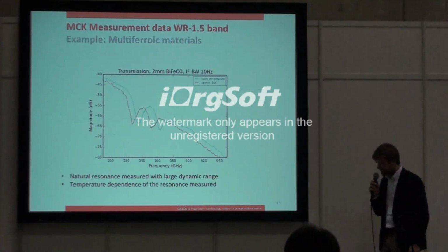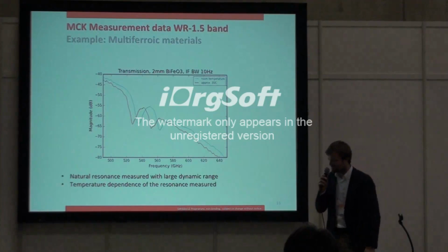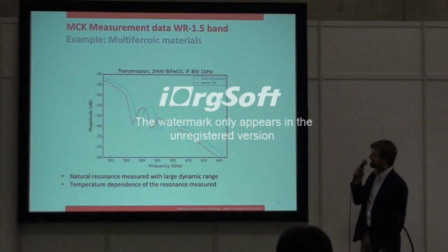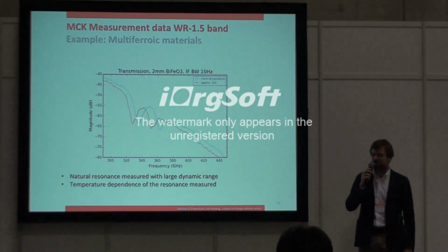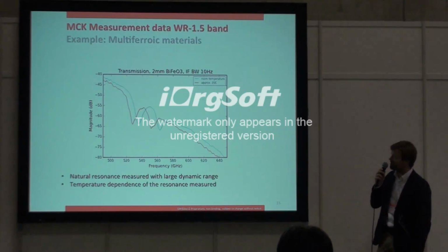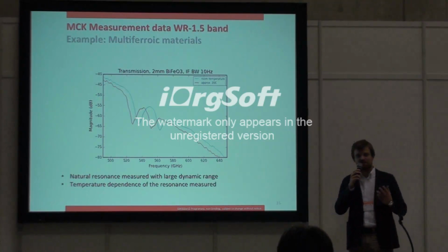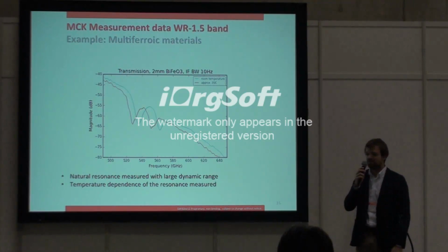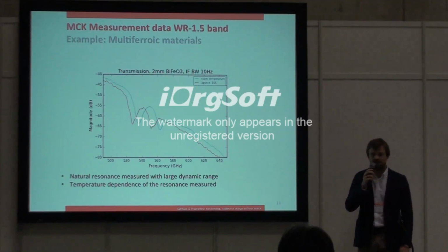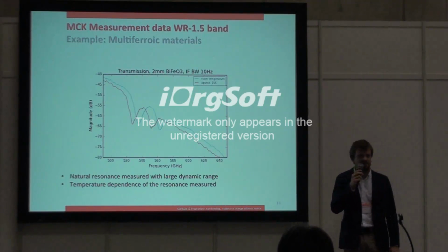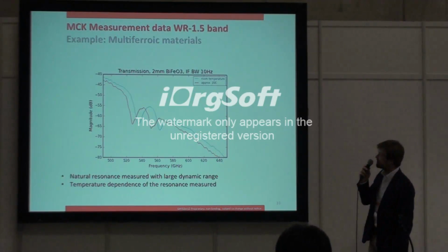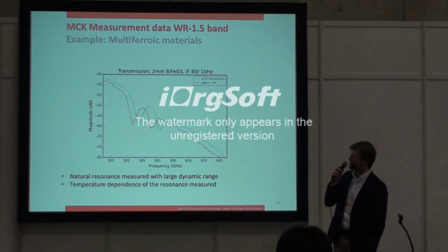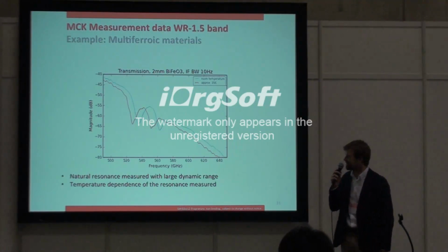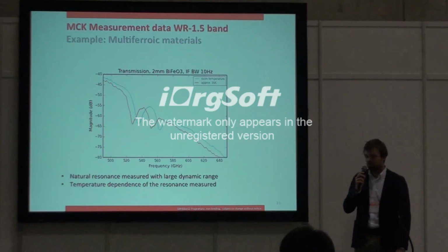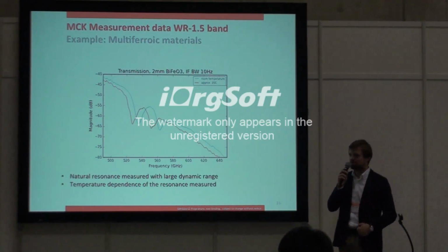One example of those is our Swiss Technology Institute, a laboratory working on spin dynamics, uses our device, and recently made a measurement on multiferroic materials. So these are magnetic materials that express a spontaneous magnetic resonance at a given frequency. And that resonance frequency depends on temperature. So you can compute that for this material, BiFeO3, you have a theoretical double resonance around 550 gigahertz, which by inserting the material in our measurement fixture, we were able to measure with a simple transmission measurement.